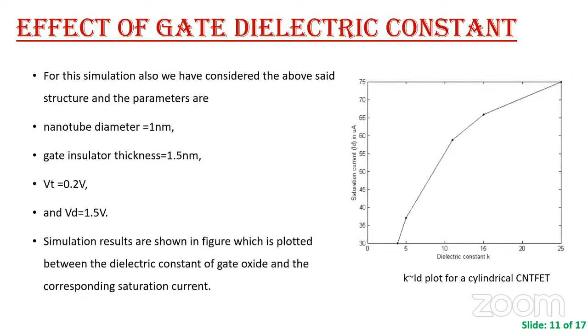and the effect of gate dielectric constant. For this simulation, we consider nanotube diameter 1 nanometer, gate insulator thickness 1.5, Vt 0.2 and Vd 1.5. We can clearly say that the saturation current increases with increasing dielectric constant, but the degree of this positive effect reduces as we go to higher dielectric materials. This means that as we go to higher and higher dielectric materials, the increment in ID with respect to K reduces. The simulation results are shown in the figure between dielectric constant of gate oxide and the corresponding saturation current.